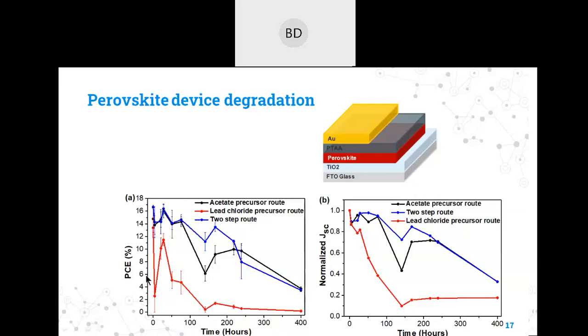The degradation in the perovskite device efficiency comes due to degradation in the current. If you see in this figure, the current has been degrading so fast for the lead chloride route film, because once you put the film or the device into the humid environment, the perovskite starts disintegrating and the amount of the perovskite is going to be lower. So if you reduce the amount of the absorber material, then overall the current generation will be reduced. So it is governed basically by the degradation in the current.